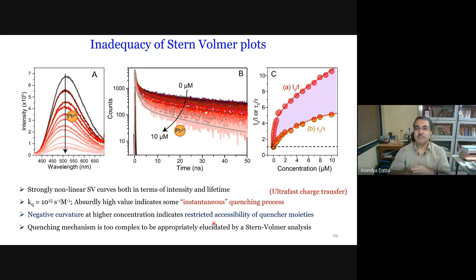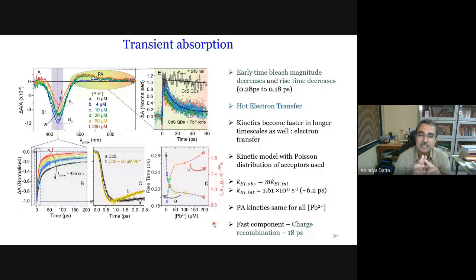So if you calculate the bimolecular quenching constant maybe from the initial part or something, we get an absurdly high value. And we say it's absurd because conventionally what we think of dynamic quenching is that it is a diffusion controlled process. Now, of course, a diffusion controlled process cannot really have a rate constant that is as high as this. So we knew that it doesn't work, but we ended up demonstrating that Stern-Volmer analysis is not really what you would like to do when you talk about PL quenching of nanoparticles. The approaches that one can take are, first of all, one can think about what is the correct decay model. As we said at the beginning, multi-exponential decay model is the most used and perhaps the most abused model. So that is one thing that we are thinking, and here we have help from papers published in 1965, 1970. People have actually proposed many different decay models.